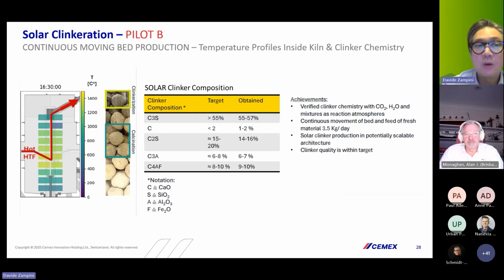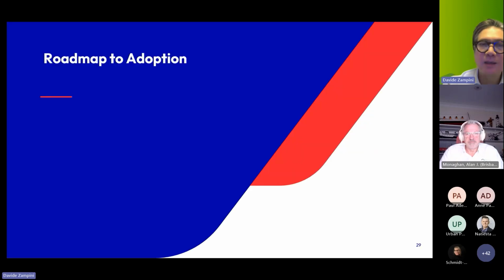as shown here. You can see the temperature profile that we documented. There's a clinkering zone and a calcination zone, and we can see that in the end, we can even produce the solar clinker in a continuous fashion, complying with the clinker chemistry that we need. So this is all very promising, and it's showing that we're step by step de-risking the technology.